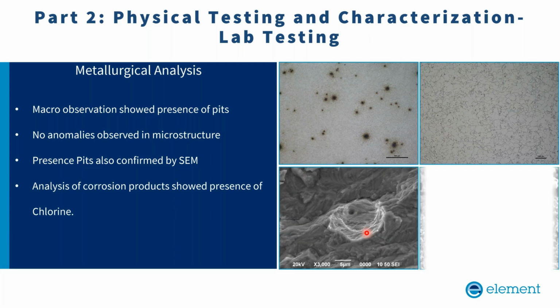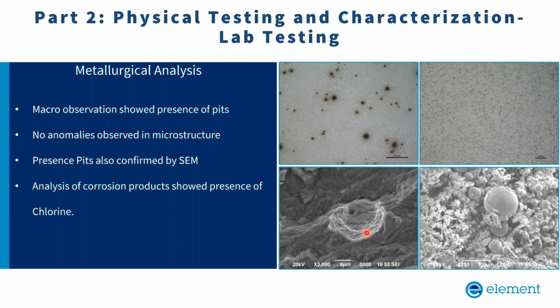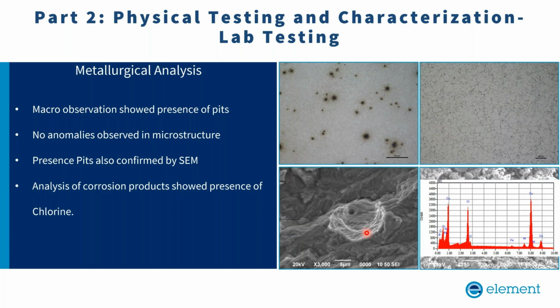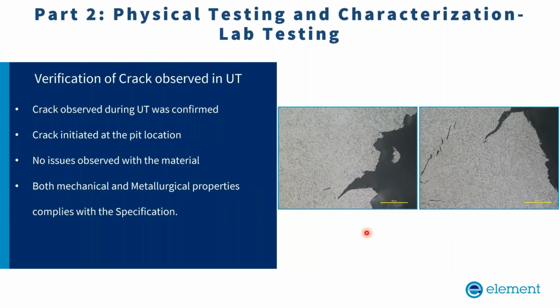Analysis of the corrosion product was done, and it was observed that chlorine is present in these impurities. So it confirms that corrosion is related to exposure to chlorine, which caused localized pitting of the material, and this is the main cause of failure, the corrosion mechanism in this material. We have done further analysis of the component where a through thickness crack was observed during UT measurement.